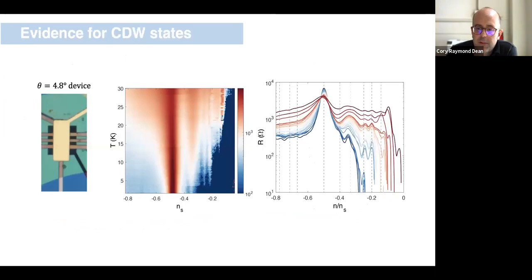Okay, so one last thing, the final thing we noted in these devices, was that if we looked more carefully in the low density regime, so here, again, this is the half filling peak, plotting temperature versus density. If we go to very low density, but we go to higher temperature where things are not totally frozen out, and we can resolve some transport features, then in that case, we see multiple oscillations in our data. And those oscillations, it appears, we can coincide with fairly well-defined fractional fillings.